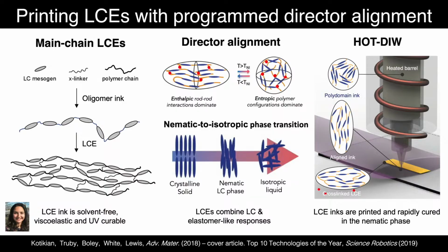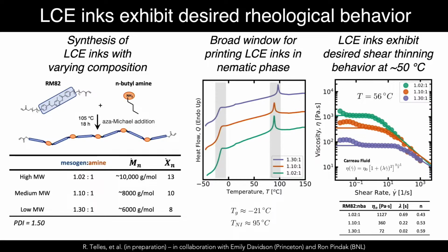The idea here is that we print in the form of oligomers, so they're just long-chain, single-chain macromolecules. Then we lightly cross-link them after printing using UV curing, and that allows us to lock in the shear-induced alignment so that we don't have a loss or degradation of that alignment. Having that UV curing step is very important. We also do this in the nematic phase, as I'll describe in a bit more detail. Here are some examples of different mesogen to amine ratios that we've looked at. The data I'm going to highlight today is almost in this 1-to-1 regime.